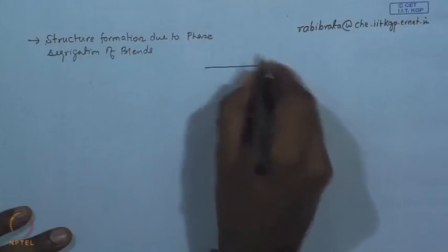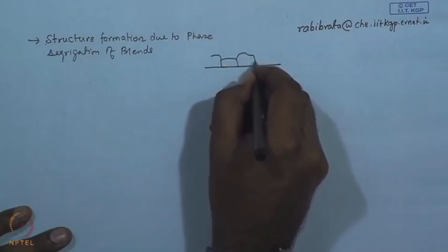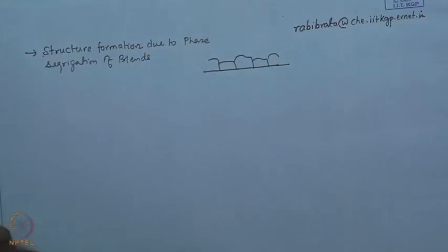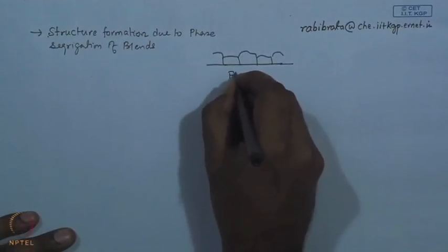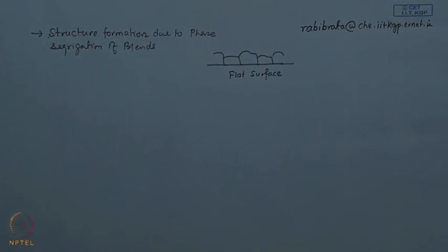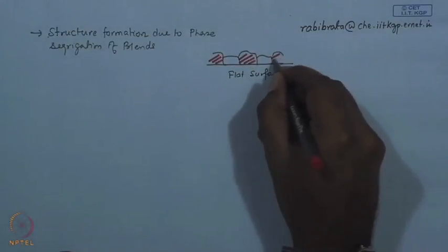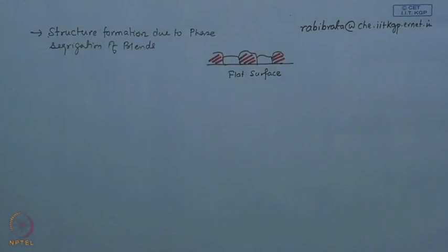You can have a look at some of the aspects. So, you have two polymers in the system, let us say the proportion is A is to B, and if you spin coat on a flat surface, you see some morphology. The relative proportion of the two polymers and the extent of surface coverage by each of the phases do not match. So, let us say 60-40, the phase which has a 40% volume fraction covers more or less than 40% of the surface.